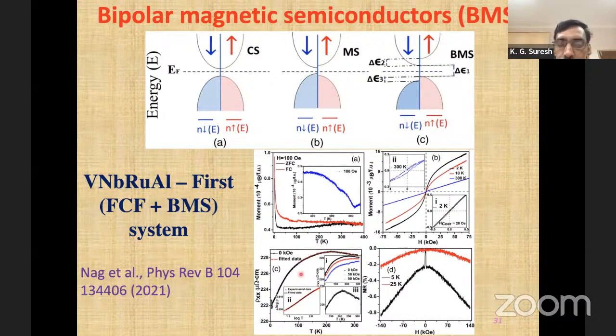We have identified this system as one of the first systems where we could show this. Again, you can see that the magnetic moment is very small. It has all the properties that we expect for a semiconductor. But from experiment, as I mentioned, you cannot tell what kind of semiconductor it is. At the most, you can tell that it's a gapless semiconductor or a normal semiconductor. Nothing more than that is possible from the experimental data, even if you do it more carefully.